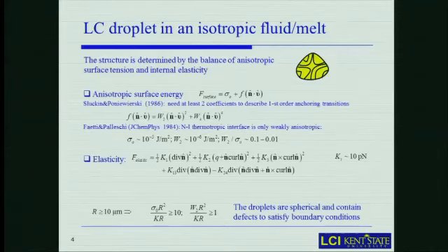So from the estimates above, yeah, by the way, I've forgotten to mention that experimentally, the order of magnitude of K is 10 piconewton, and you can find an estimate in de Gennes's book for K as simply the temperature of room temperature at which many liquid crystal melts divided by the characteristic size of the molecule. That would give you about 10 piconewtons.